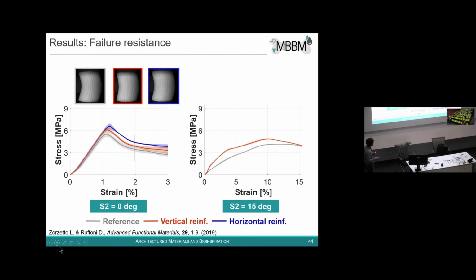And what is interesting is what is happening when we add, for example, vertical reinforcement. Now you see we are reinforcing the tilted fibers with some vertical fibrils. Well, they provide a little bit of an increase in stiffness, but essentially the behavior does not change a lot. What you see here is this collective buckling or kinking of these vertical fibers, a collective buckling because they somehow feel each other through the matrix. So as soon as one fiber is buckling, all the structure is buckling.